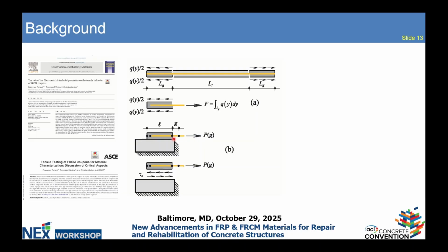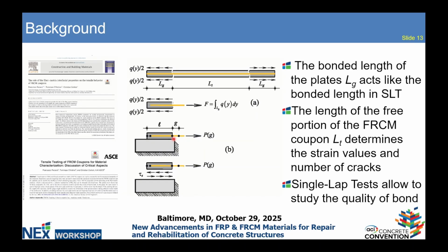Typically, in this composite, you need a fairly long length to achieve the entire transfer length. And so the problem is, this means that your plates need to be fairly long. And if you don't do that, you're not going to achieve what is the potential of this composite. So again, in summary, the bonded length of the plates acts as the bonded length in single lap test.